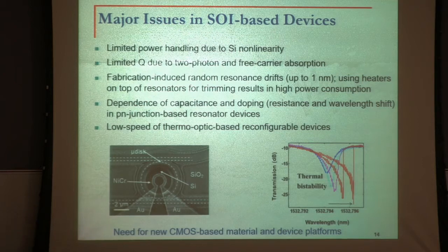But when you fabricate it, it's not going to be that size. There's a little bit of fabrication imperfection that changes the resonance wavelength. Now, for publishing a paper, you don't care, because you have a tunable laser, and you tune it to that wavelength, and then you report what you want. But if you want an array of these, each one of them modulating a frequency or wavelength for a WDM, then you do care. So you always have to trim your structures, and that has to be low power.